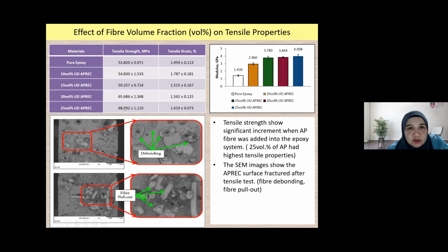It increases to 68 MPa for tensile strength when we add 25 volume percent of Arenga pinnata, tested in unidirection. The modulus without any fibers is about 1.43 GPa, and it increases to 4 gigapascal if we put 25 volume percent of Arenga pinnata.